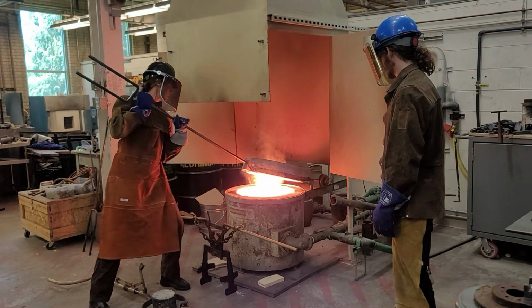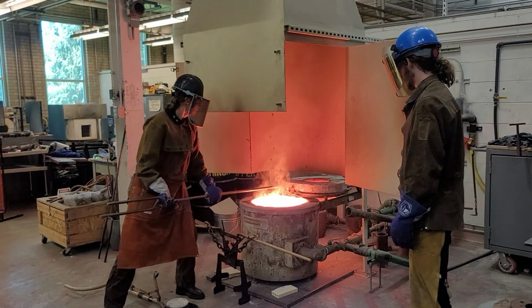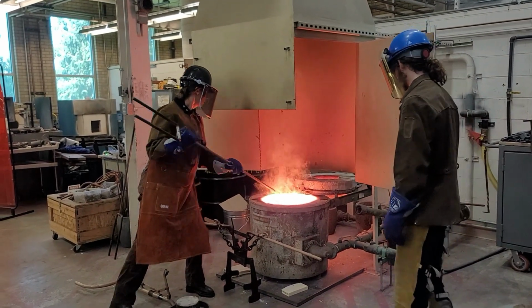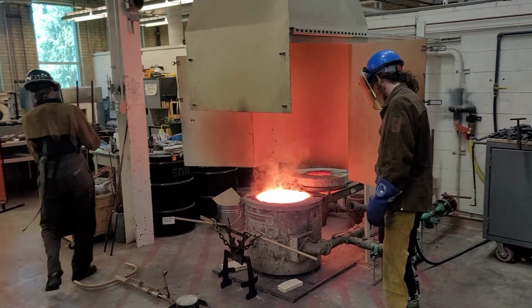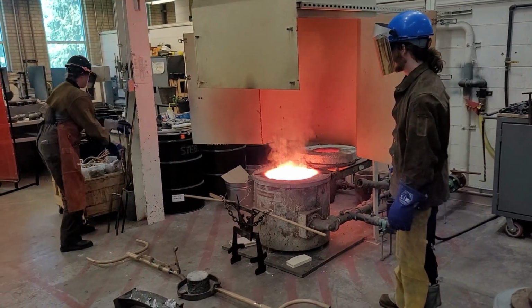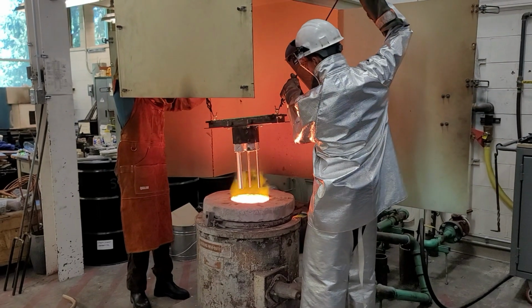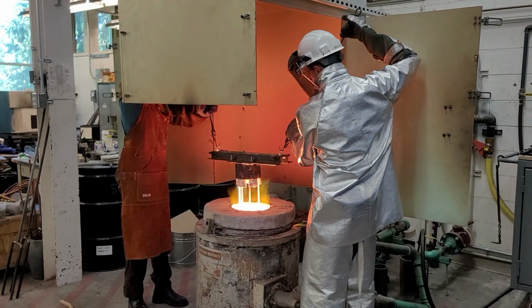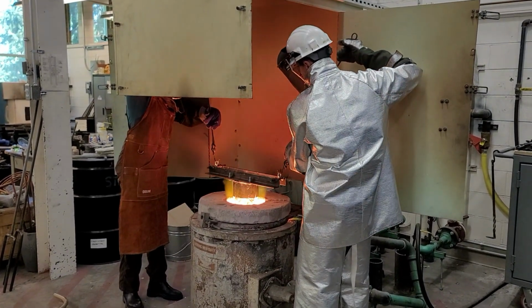The first static dwell test was designed to address the feasibility of specific refractory materials for use in our MRE reactor. The refractory materials chosen include boron nitride, alumina, molybdenum, and silicon carbide. These refractory materials will be submerged in a regolith melt with both anorthositic and basaltic compositions at temperatures of around 1300 degrees Celsius for durations of roughly 1 hour.